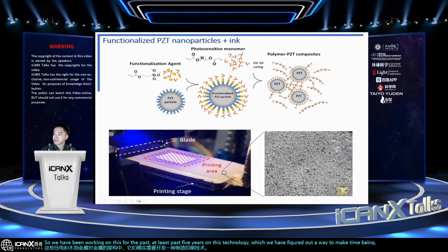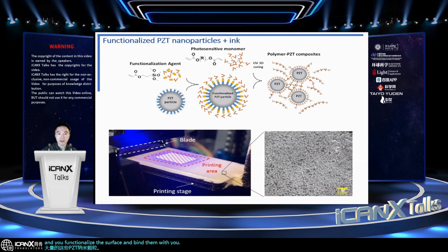So it started with a large quantity of these PZT nanoparticles, and you functionalize the surface and bind them with UV sensitive monomers, and then make it into a photocurable ink, which is basically a highly concentrated piezoelectric ink with these piezo nanoparticles in between our UV sensitive monomers, which basically serve as a binder. Then you can use 3D printing technology to print them.